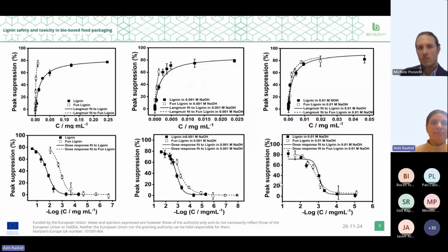So here I have compared the reactivity of the unfunctionalized lignin with the functionalized lignin under different amounts of sodium hydroxide used. Again, the top plots are the Langmuir fitting, and the bottom plots show the dose response fitting.